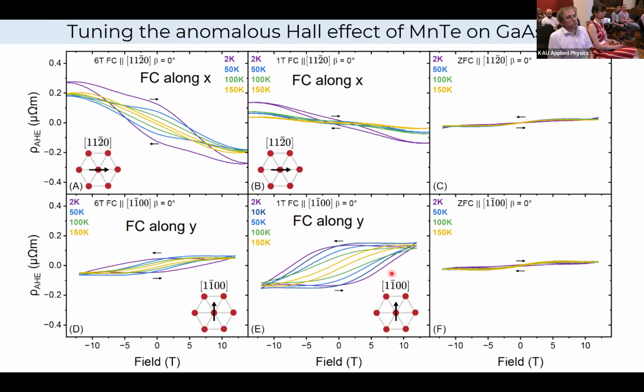More questions? Yeah, I just wanted to ask whether you tried to make a really single layer, like in iron selenium, for example. Are you working in this direction or not? Single layer manganese telluride? Yeah. So single layer is pretty tricky to make for transport because there's still a finite roughness. These materials aren't perfectly flat. If you look at the surface, there's some roughness on the order of 2 to 4 unit cells. So if I make a single layer, it's very likely that there are regions that are bilayer, maybe even 3 layers. So that's very tricky, and it's not one of our priorities right now. But there are probably experts in STM that are working on that, and I think STM is probably more suitable than conventional transport to do this.